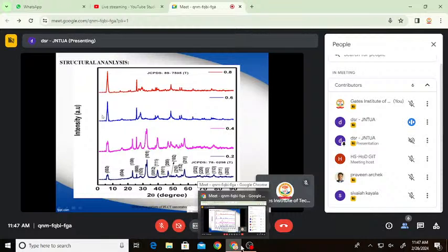Further, the structural parameters such as a, b, c, that is lattice constants, crystallite size, bulk density, X-ray density, porosity, volume of the unit cell, and specific surface area are also calculated. It is found that the lattice parameters were reducing with the increment of lanthanum composition, which may be due to small ionic radius of lanthanum cations rather than lead cations.